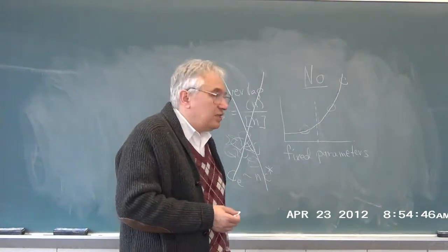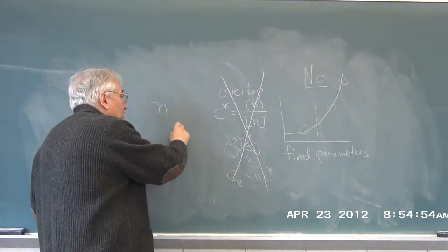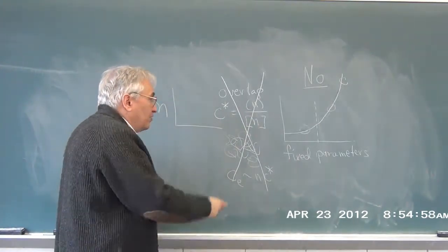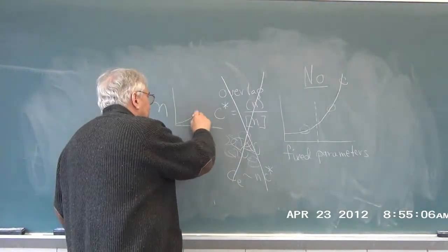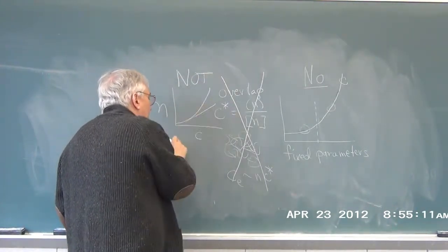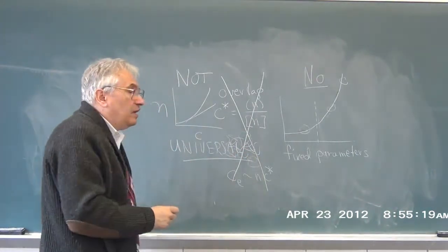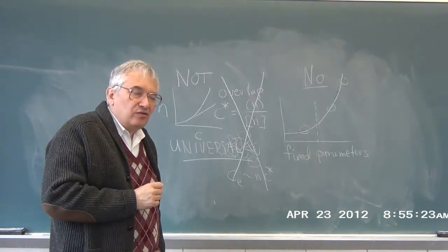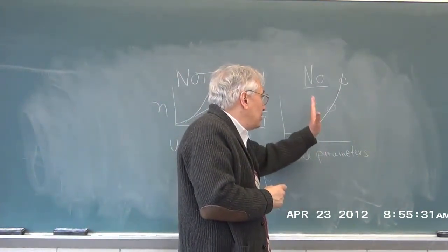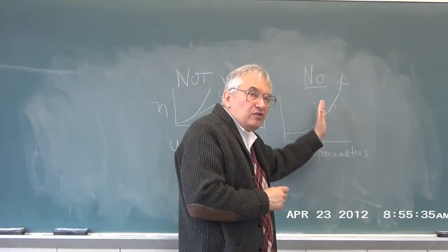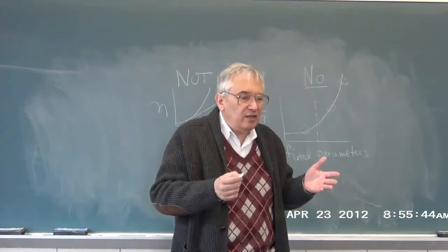The only exception to this is the solution-like, melt-like transition, but there we have an important issue. You might say the solution-like, melt-like transition is an example of the crossover here, except, of course, that it's only seen in some systems. Not universal. The viscosity is not a universal function of the polymer concentration, and that isn't very good for some of these models either. However, the important issue is that if you look at most sets of measurements like self-diffusion, and you look someplace near the overlap or so-called entanglement concentration, nothing odd happens there, and there's not really a crossover, anything like that.